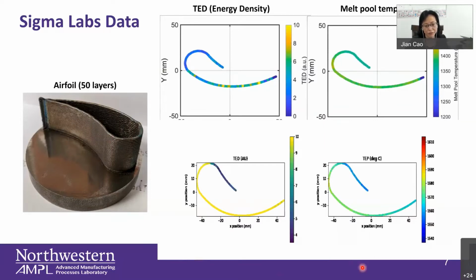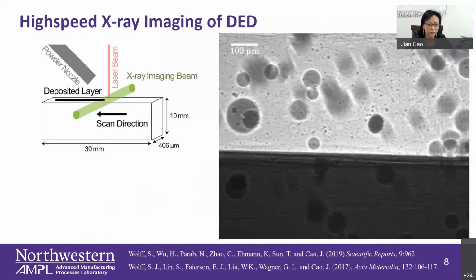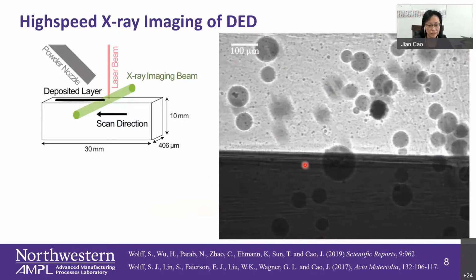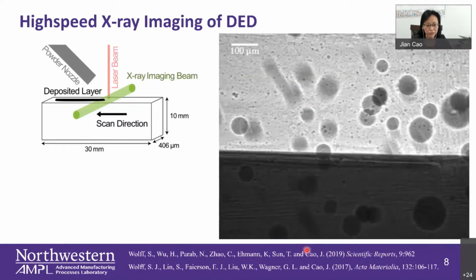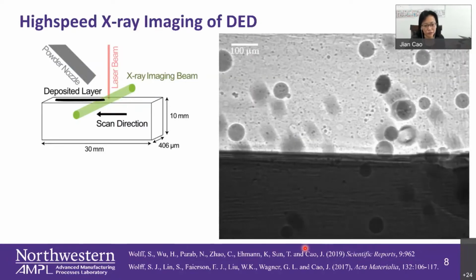And the nice thing about this one is really the high resolution in terms of both temporal and spatial resolution. For spatial resolution, you can go down to 6 micron fine details. And if you combine that with the IR camera, you won't be able to get this kind of 100 kilohertz. So what we are trying to do is to utilize this to understand the process and material properties, as well as try to control that. The other thing that we have been doing is understanding how the porosity actually forms in the DED, and meanwhile you want to control the porosity.